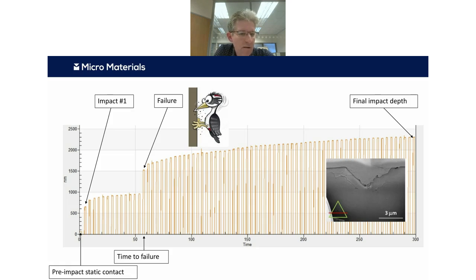So if you have, for example, an acoustic emission sensor, which is actually done in this work, we're not showing it, you can get a distinct peak in the acoustic emission just at that particular impact corresponding to that cracking. And then you can use focused ion beam again to look and see these crack networks that form subsurface. So again, as I say, it's a very powerful test technique for looking at fatigue and fracture.